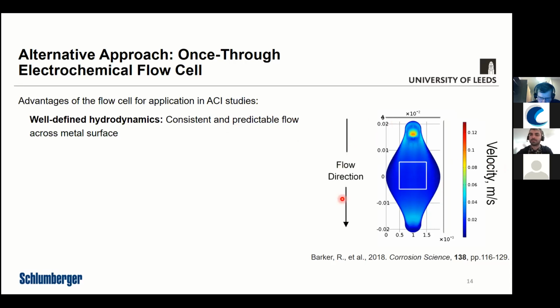And this is some computational fluid dynamics modeling that we did a few years ago now, where we predicted the fluid flow velocity over the carbon steel coupon through that gasket shape. This gasket is a particular shape, an eye-shaped gasket. Other research we've done at the University of Leeds, not by myself but by another researcher, looked at the most ideal flow designs for flow cells so that you avoid any recirculation. Recirculation would be bad because you can end up with areas where you trap fluid. It won't necessarily flow through the cell very well.